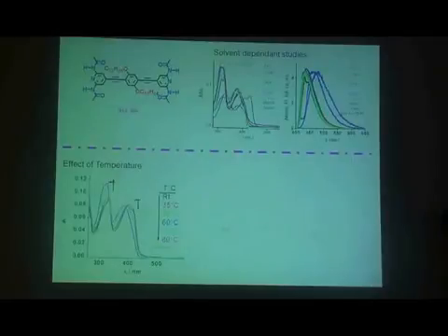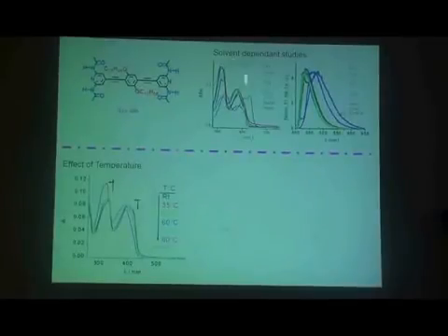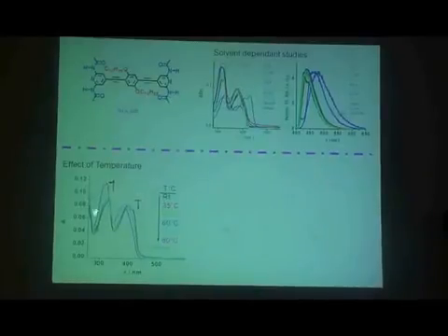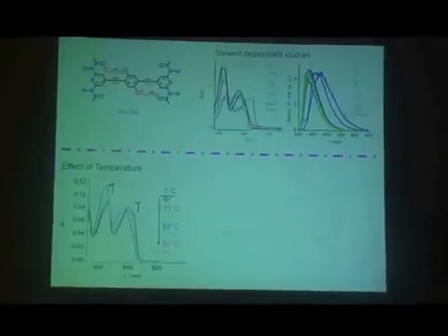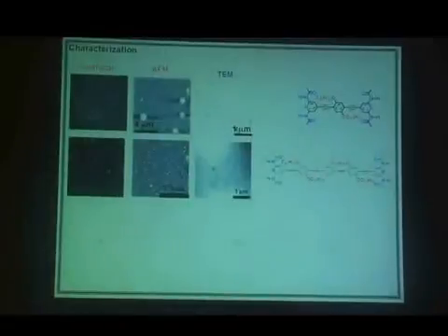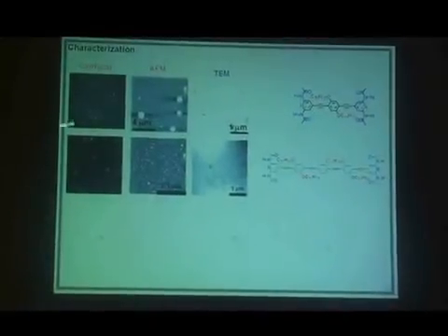So that is made clear by increasing the temperature. When you increase the temperature, you give a lot of energy to the system. So all these molecular interactions break and it comes to the individual molecule. There is a blue shift of this absorption spectrum when you increase the temperature, and finally you reach something similar to that of the other solvents. So you see that they are undergoing aggregation, and what you see is the formation of